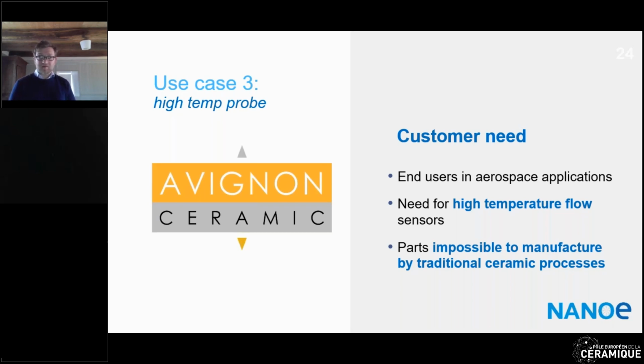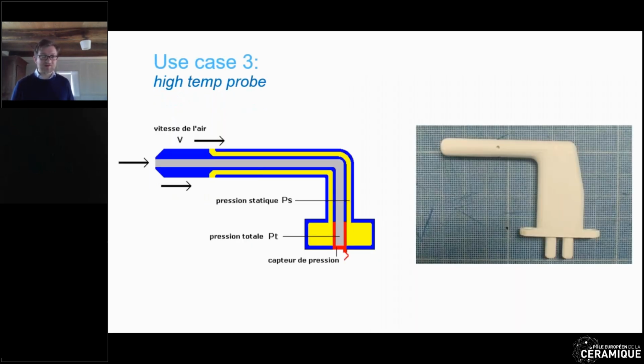And the part itself is quite simply impossible to manufacture by traditional ceramic process. Why? Because you have a lot of internal channels. Here you can see the principle of these probes. It's a probe that allows you to measure the speed of a flow by measuring the difference between the static pressure and the dynamic pressure. And for that, you have a hole in front of the probe, which you can't see on the picture, I'm afraid, which goes in one of the two channels, and then 4 holes on the side of the part, which goes in the second channel, and you measure the difference in pressure between those two.